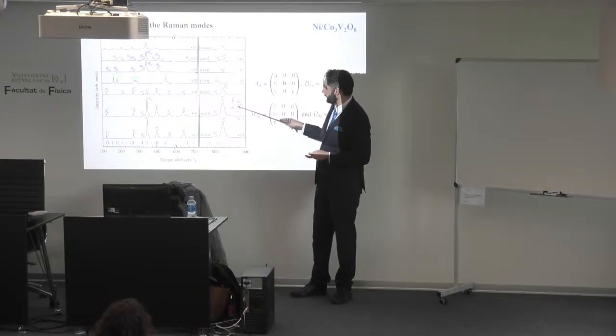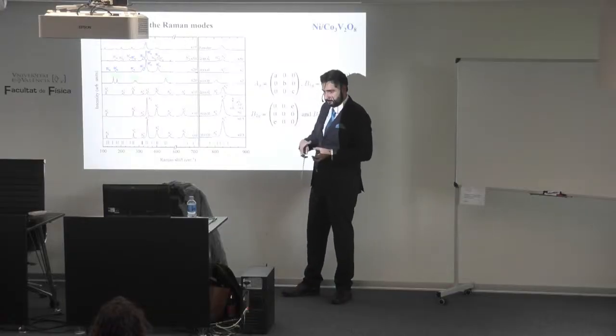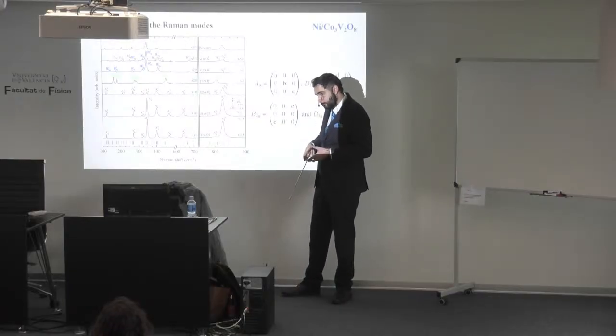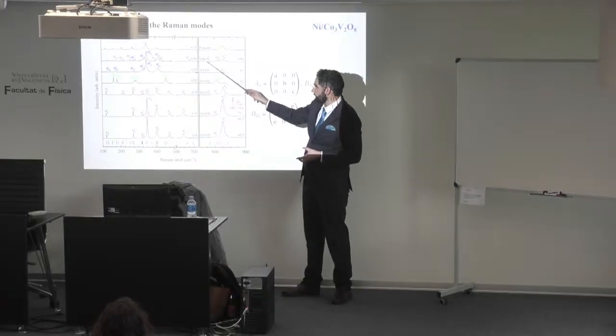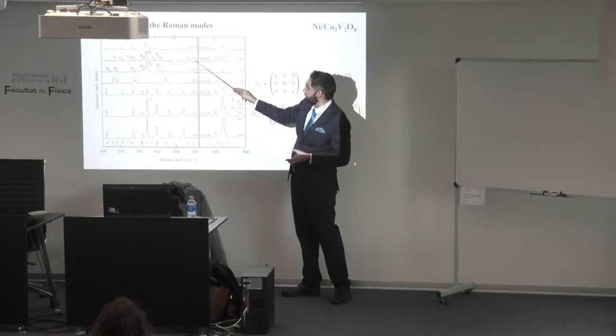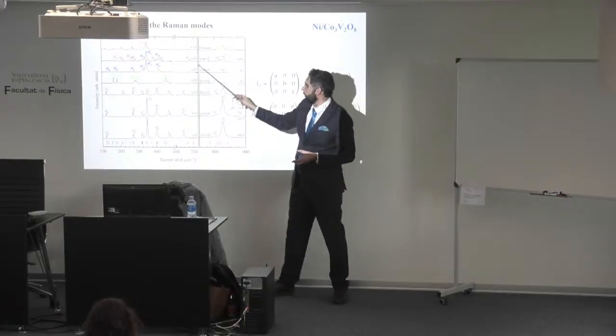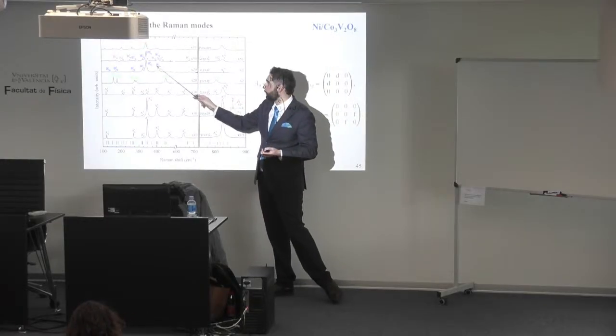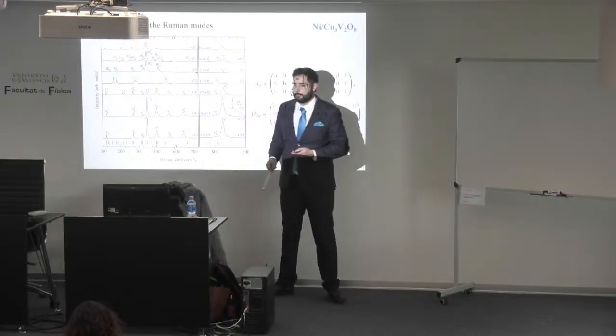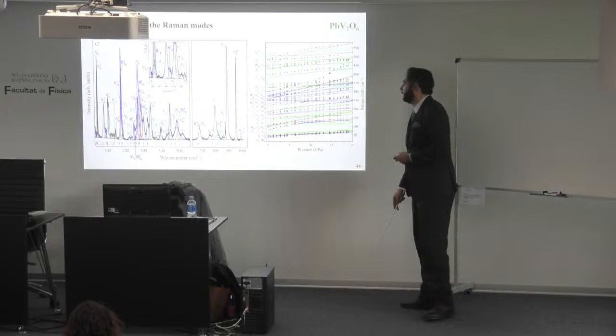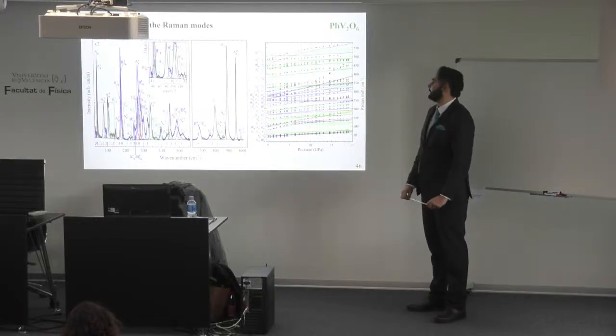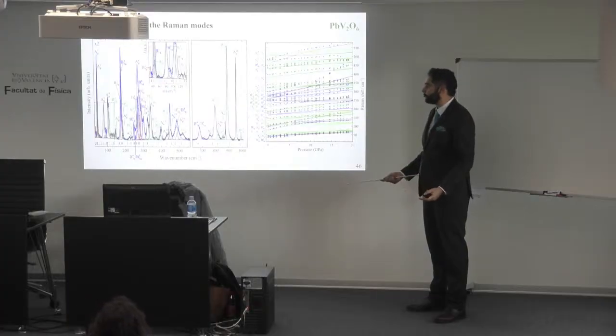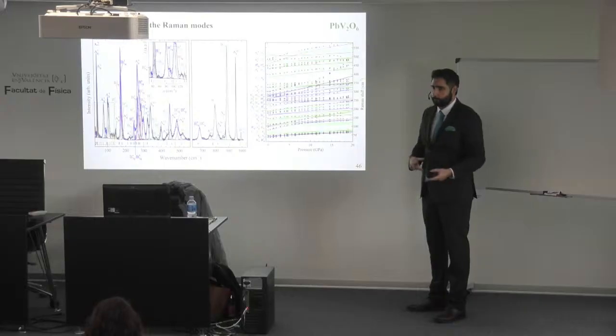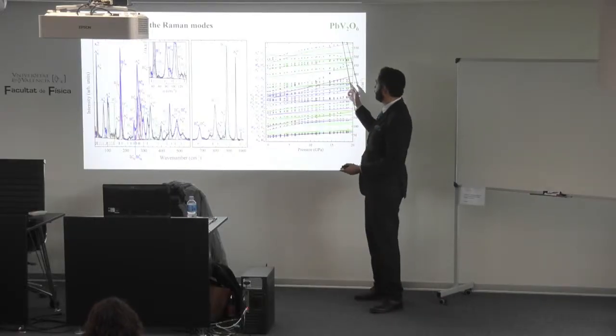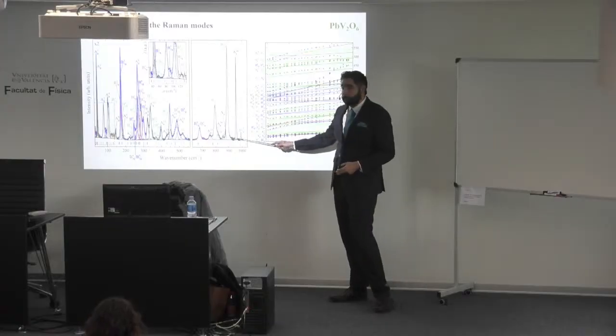So we started in the Z phase and we rotated 33 degrees. So this phase, called it in a different letter, has contributions of both B1 and B3. And as we already know B1, we can get the B3 contributions. This is a different case. This is not the ideal one, but it's something that also works in order to relate the symmetry with the modes. This case, we have for lead metavanadate 54 modes.